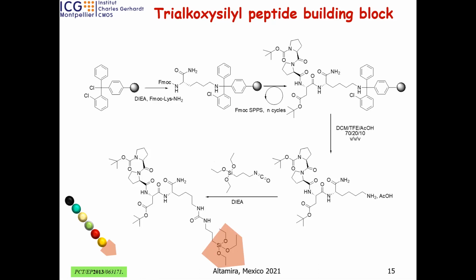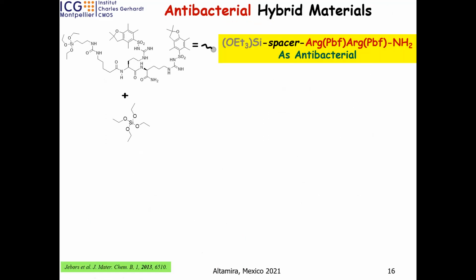You have to avoid water. Why? Because this tri-alkoxysilane is very sensitive to water. In water without catalyst, it's no problem, but you know, we sometimes have some acid and some base. So avoid water. It's important to get your silylated precursor pure.